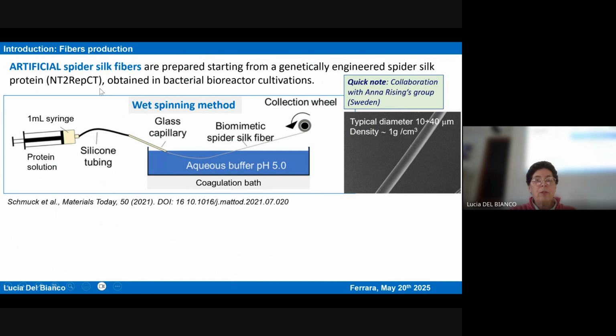And they also found a very efficient and green method to spin the fiber. This is done by preparing a protein solution, mostly aqueous, which is extruded using this syringe into a coagulation bath, also mainly based on buffered water, where the fiber forms, and therefore they can collect hundreds and hundreds of meters of continuous fiber, which is light, the density is very low, and the typical diameter depends on the syringe, but is some tens of microns, between 10 and 40, let's say.